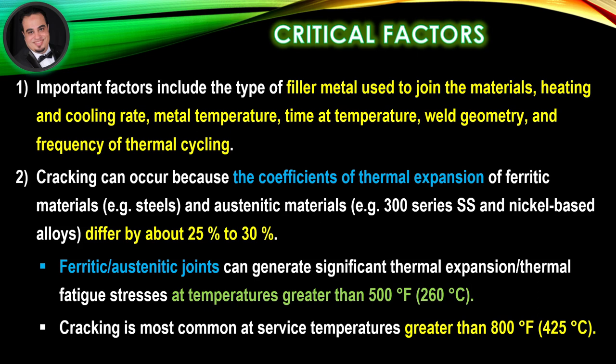Primarily on the ferritic side: the higher the operating temperature, the greater the stress created by the differential thermal expansion between the metals. Ferritic-austenitic joints can generate significant thermal fatigue stresses at temperatures greater than 500 degrees Fahrenheit. Cracking is most common at service temperatures greater than 800 degrees Fahrenheit.